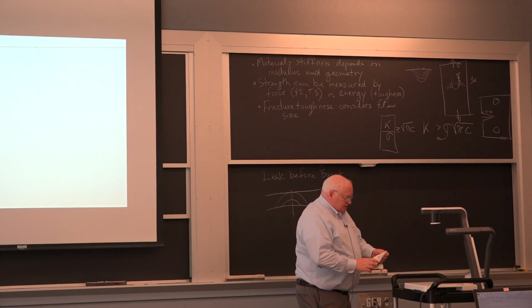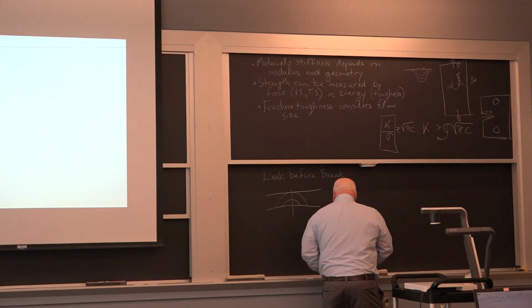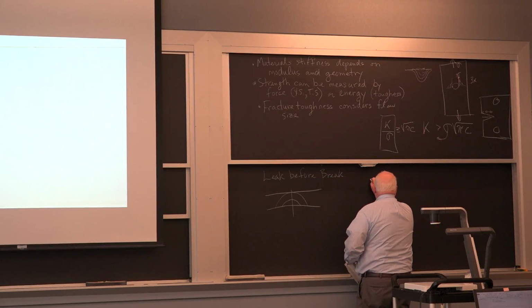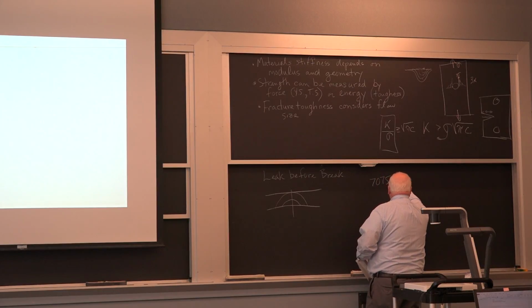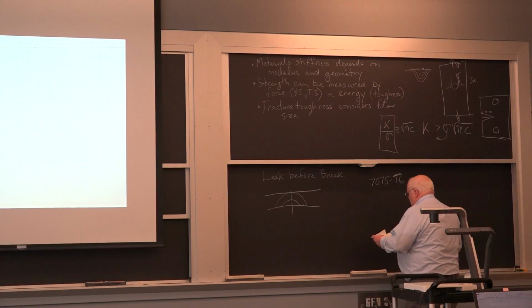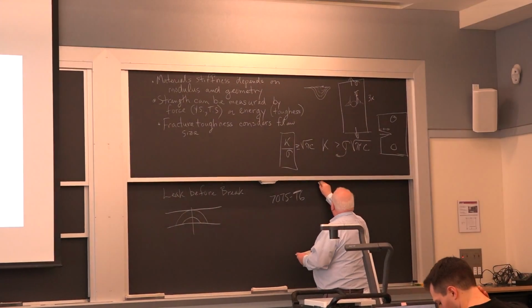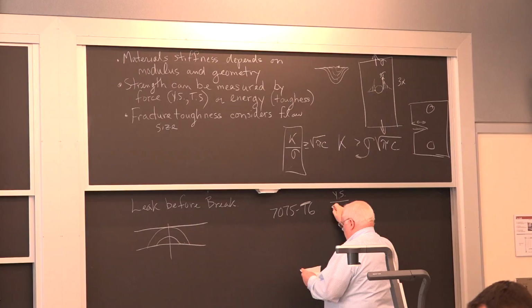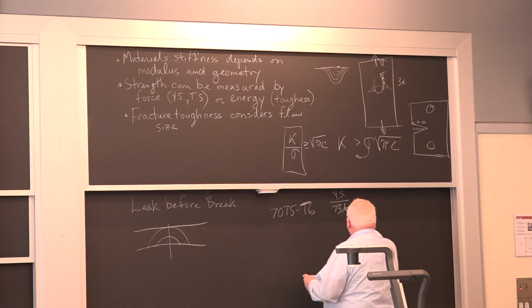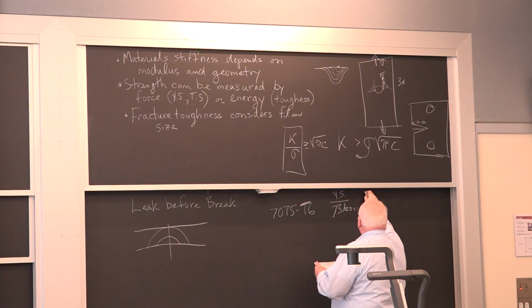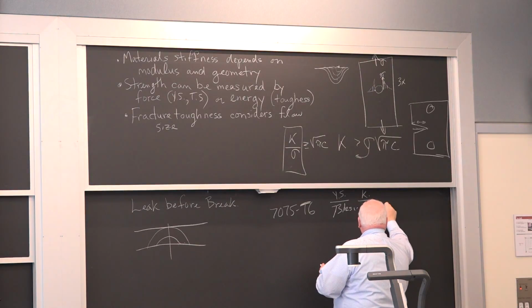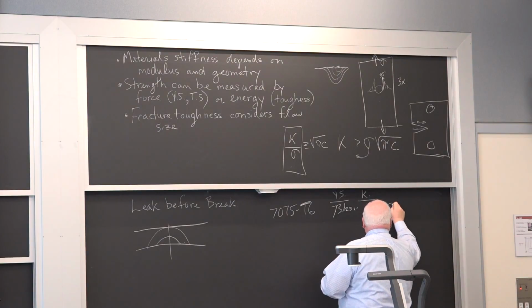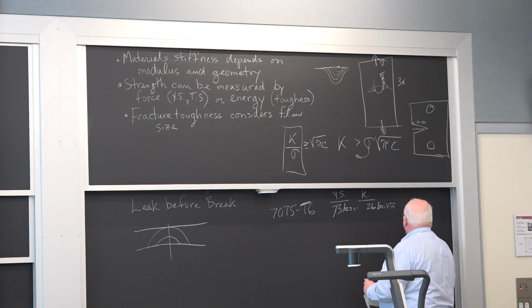And so here's what he had. That piece of aluminum tubing was 7075 T6 heat treatment. So it's heat treated to the T6 condition. And it turns out, if you look in the literature, the yield strength of that material is 73 KSI. The fracture toughness is 26 KSI square root of inch. And the wall was 1/8 of an inch thick, 3 millimeters.